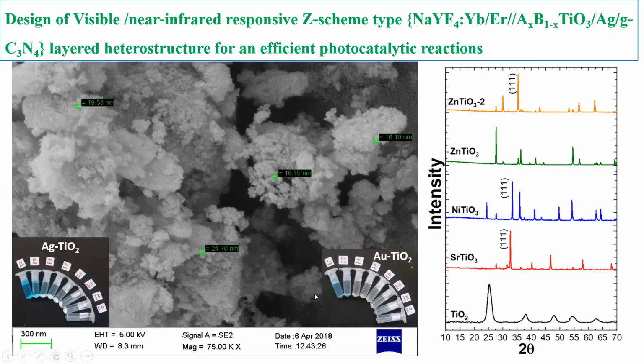And I already studied dye degradation, like water purification. So I found that within 20 minutes, we could purify the water. General TiO2, what people use, takes up to 90 minutes. We cannot consider it water purification, it's not drinking. This is a methylene blue dye degradation study we generally propose for this type of research.